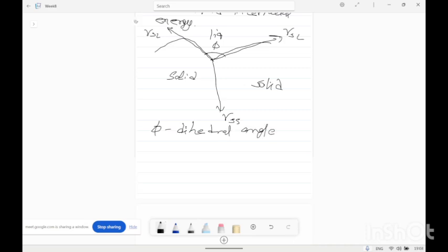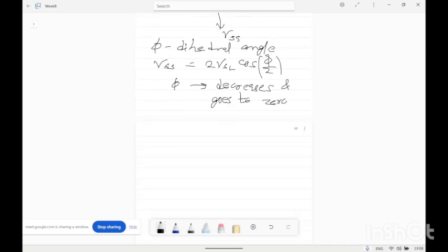So the relation between interfacial energies, the solid-liquid interface and grain boundary energy, is written as gamma SS equals 2 gamma SL cos phi by 2. In this relation, if the dihedral angle decreases and goes to 0, the value of cos phi by 2 will be 1. That will lead to the relation gamma SS equals 2 gamma SL, meaning the grain boundary solid interface energy is 2 times higher than the solid-liquid interface energy.